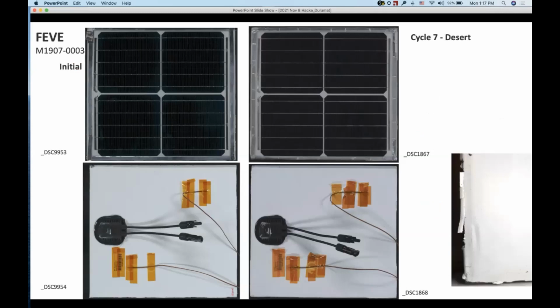So next we're moving to the FEVE type sample. And here's the initial on the left, and on the right is after 7 cycles. And what we're seeing is a lot of embrittlement on the perimeter.